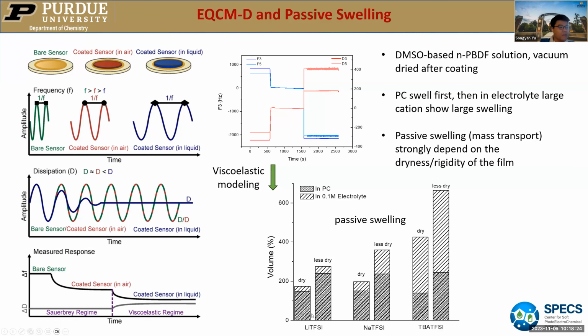So I compare the n-PBDF under lithium TFSI, sodium TFSI, and TBA TFSI, into PC first, and then into the electrolyte, the three different electrolytes. First, we can see that in the PC, they have basically similar swelling. But then we put it into electrolyte. The one with lithium TFSI has the smallest swelling, and the one with TBA TFSI has the largest swelling. This is understandable because TBA is bulky and heavier. It enters the polymer and largely expands the film.